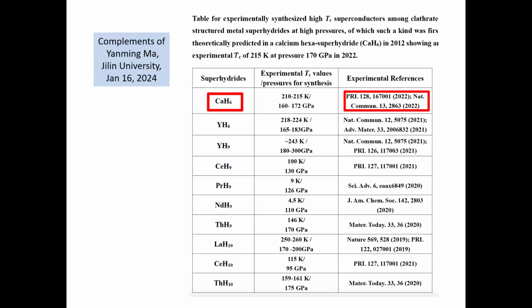Okay, as I was going 2 years ago to a workshop at the University of Maryland, a couple of days before, I wrote to Yanming Ma and asked him what metal hydrides under pressure he believed to be superconducting, his group and whatever, and evaluate the papers, the results, and so forth. And he gave me this list of 10. There are actually 8 with TC above 100 Kelvin and at high pressure. There are 2 down here that are low temperature things. They have magnetic metal atoms in here, which causes a difference in TC, but he listed 8 of these for me and got the result back to me in 18 hours. So I could talk about it at the workshop.